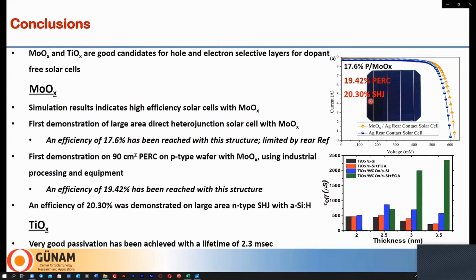Finally, we have also demonstrated above 20% silicon heterojunction with molybdenum oxide as emitter, with enhanced short circuit current density in the blue part compared to a reference cell with 20.8% silicon heterojunction. Our cell was unfortunately limited by the fill factor. And for electron selectivity, titanium dioxide was studied and a very good passivation was reached, with a quite successful lifetime of 2.3 milliseconds and 700 millivolt implied VOC demonstrated.